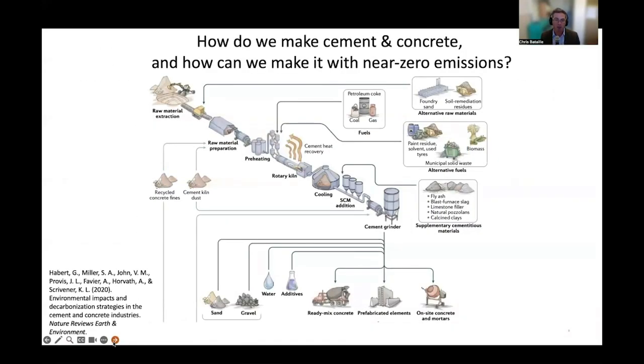And how do we make cement and concrete, and how can we make it with near zero emissions? Well, first of all, how we make it, if you start at the top left there, we have raw material extraction, which is mainly limestone. That is ground up and heated to 850 degrees Celsius. It separates into calcium oxide and CO2. That's where most of the emissions from making concrete are. That CO2 is released to atmosphere today.